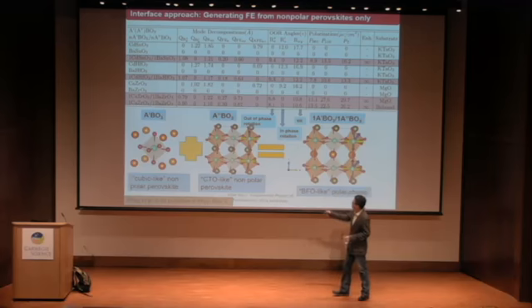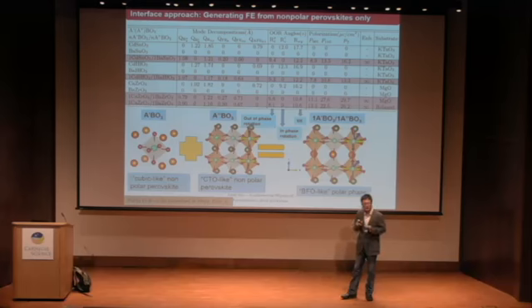Also, from the last two examples using different substrates, we can see that the substrate doesn't play an important role here, because we relax the structure with different substrates and get essentially very similar results.